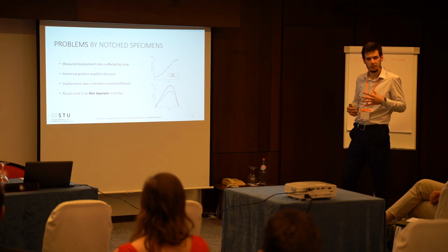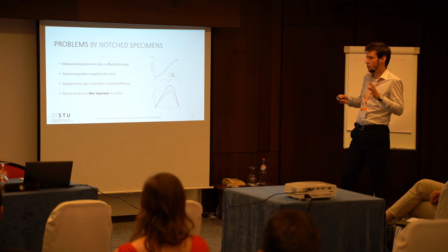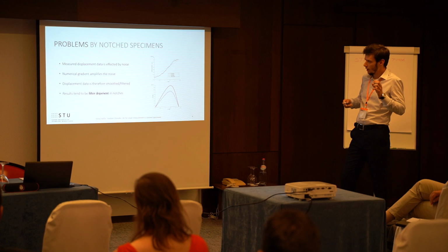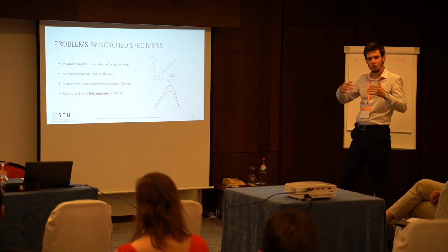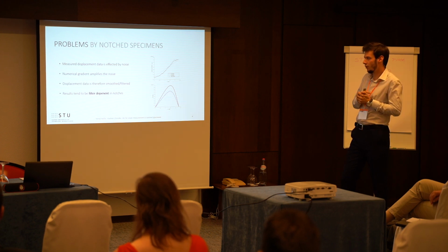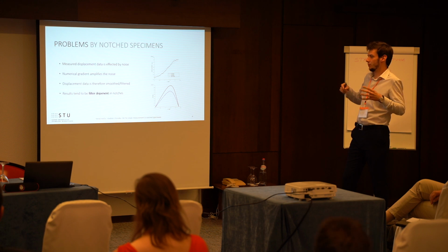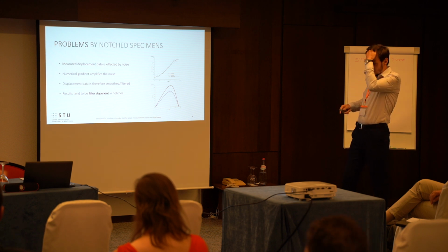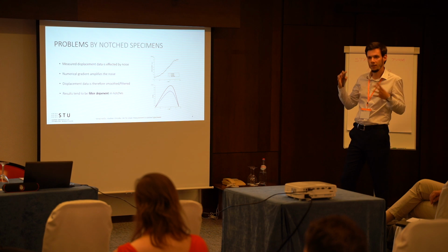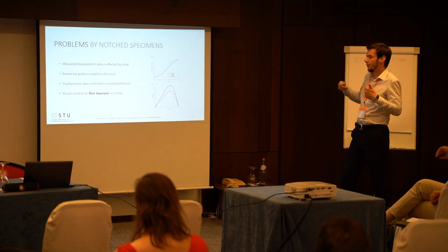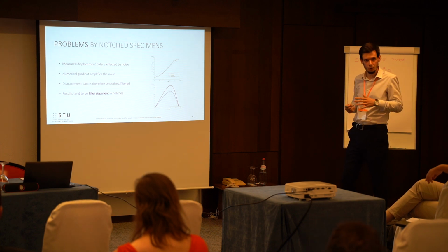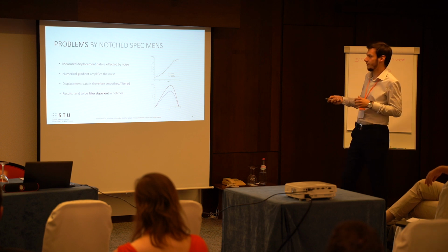In our case, it's a spline polynomial, and the smoothing is done by restricting the curvature of the shape of the surface. The problem in notches is that, most of the time in the case of small notches, the results tend to be dependent on the parameters of that filter.